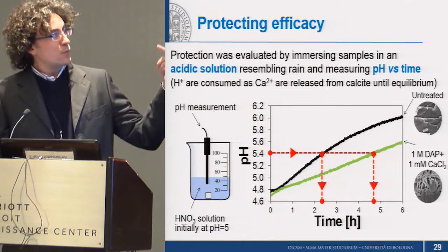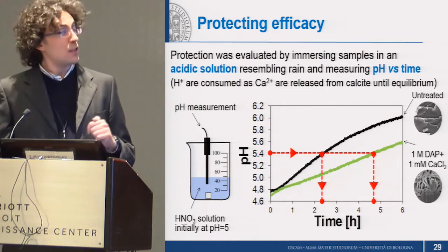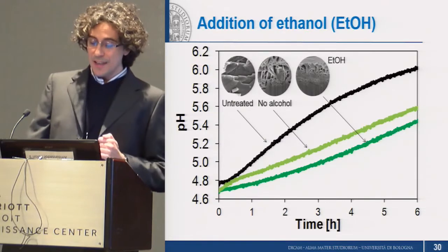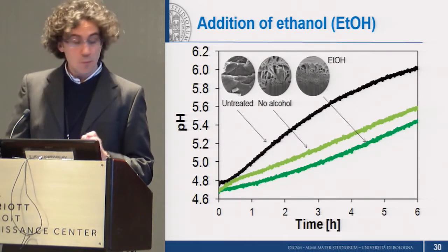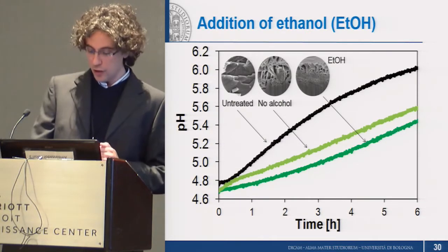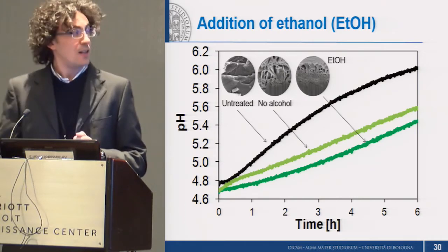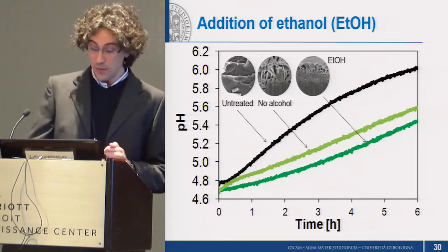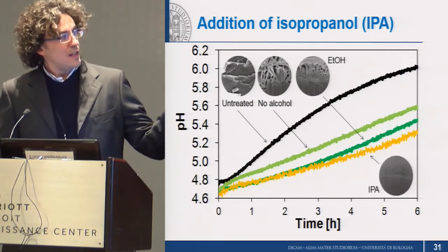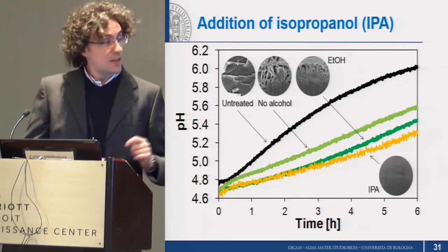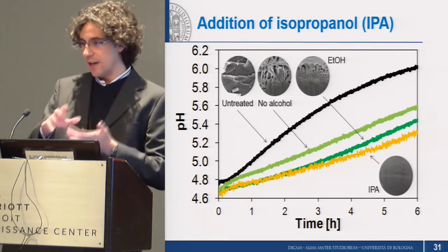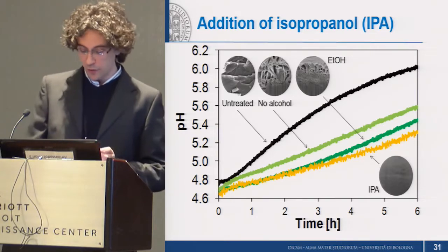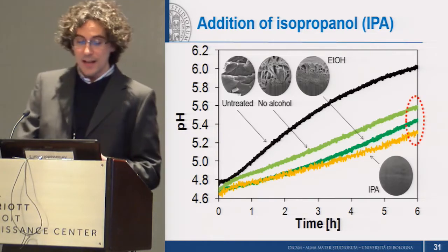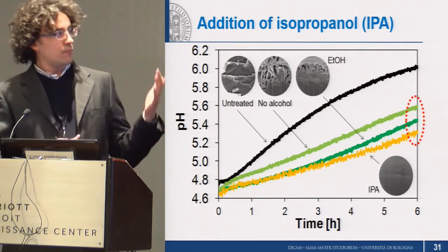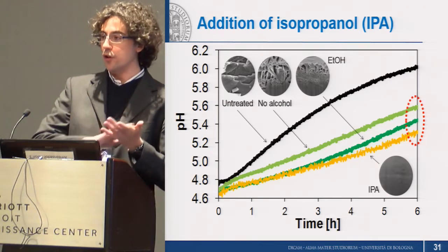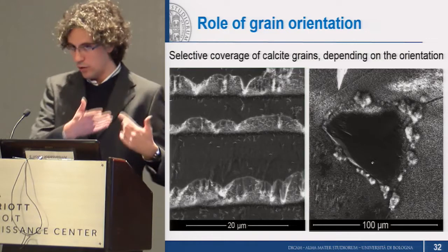We got better results when we started investigating the formulation with also ethanol addition, and slightly better results when we use IPA. Anyways, as you can see, after some time, 6 hours, all the curves kind of reach the same point, so they're not so different. Why is this the case? Because in the end, even if we can get a quite good coverage of the marble surface by all the means